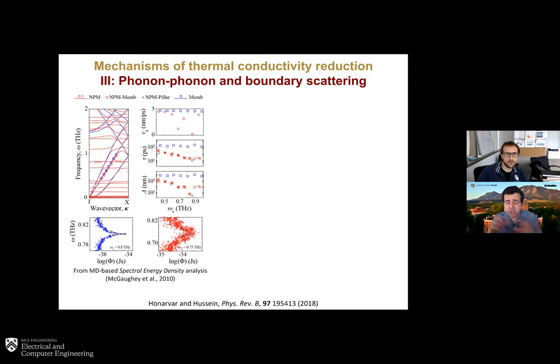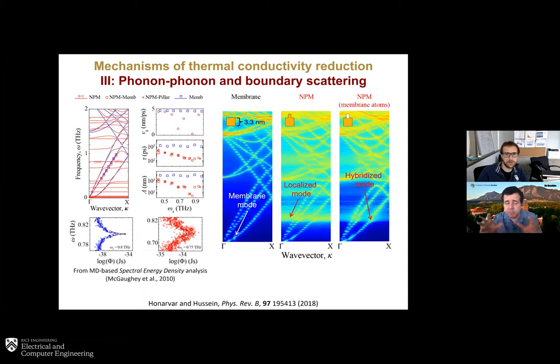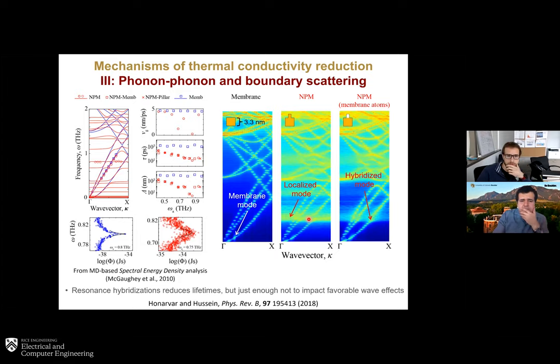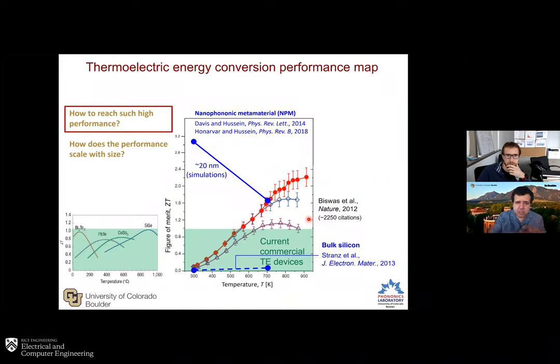And to check that, from the spectral energy density, we can actually plot the dispersion. So you can see for a pure membrane, it resembles the one that we get in the left there. The one that we have in the left is just from harmonic lattice dynamics calculations. It matches perfectly, which tells us that even in the presence of phonon-phonon scattering in a room temperature MD environment, we have these dispersion characteristics. And more importantly, once we add a pillar, we actually see the resonance modes. We see these localized modes. And that was a very important confirmation for us that this is not just a phenomenon inspired by acoustics that takes place when we look at a linearized eigenvalue problem, but it actually happens in the context of a full-fledged anharmonic MD simulation.